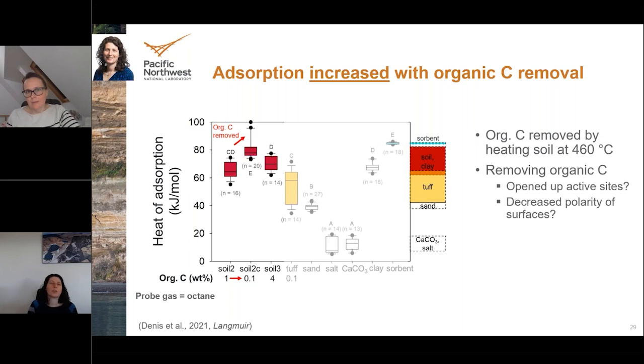Yeah, so we've tried to add some humidity to our measurements to compare, and I admit that it's a lot easier to make the measurements in oven dry conditions rather than with humidity. I think part of that is that you're trying to get controlled conditions, and with the humidity, what sometimes might be happening is that you form maybe a monolayer or some sort of layer of water on your solid surface, and then you're not necessarily getting that gas adsorbing with the material itself.